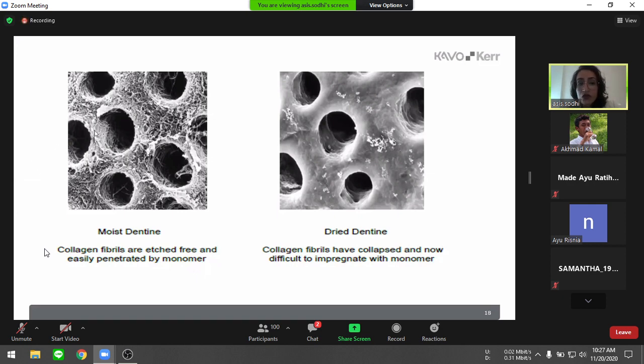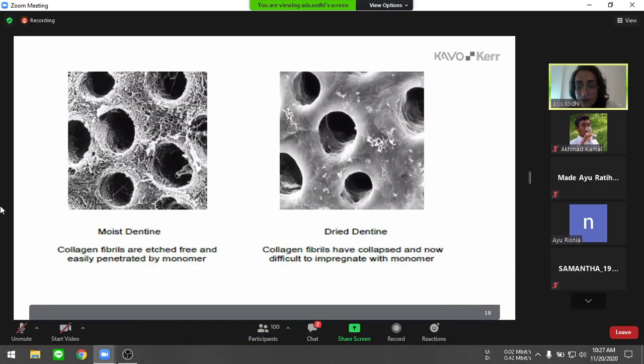A clinical tip here for you all is to remember that when you're doing this technique, a total etch technique, always visually check your dentine surface when you dry it. The dentine should be dried so that it looks glossy and moist, not dull. If it looks dull after drying, that means you've applied a lot of pressure and dried it out, right? So you will probably have to make the surface moist. However, if the surface after your drying looks glossy, that means that the dentine is still holding its moisture and it's not over dried. So the key takeaway is that when we are drying the surface of dentine after use of phosphoric acid, you have to ensure that you don't press too hard and use mild to moderate pressure to dry out the surface so that dentine looks glossy, right? So that is the visual indicator of moist dentine.